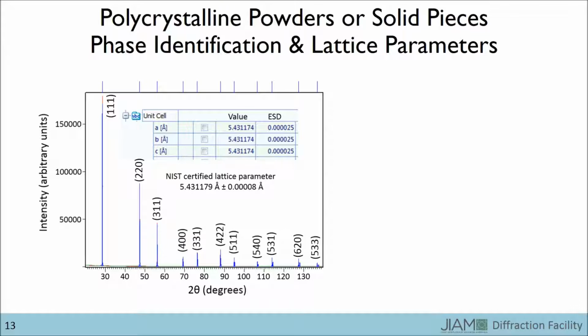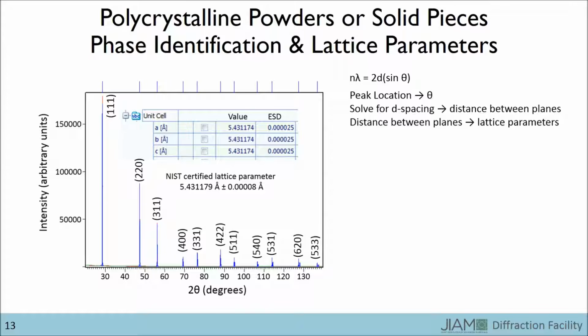This diffraction pattern can also be used to determine the size of the unit cell. If we take Bragg's law and recognize that the wavelength remains constant throughout the experiment and n can be ignored for the purposes of calculation, our remaining variables are the d-spacing and the angle. We can get the angles at which Bragg's law is obeyed by determining the peak locations in the diffraction pattern. We can then solve Bragg's law for the d-spacing of each plane for which we have a diffraction peak, which allows for the calculation of the lattice parameters.